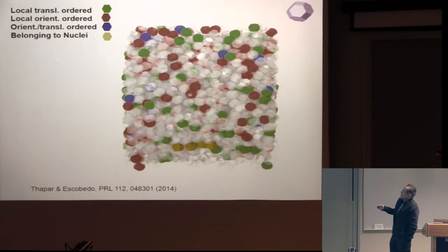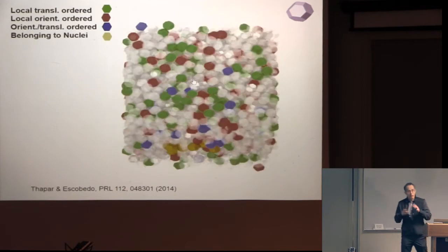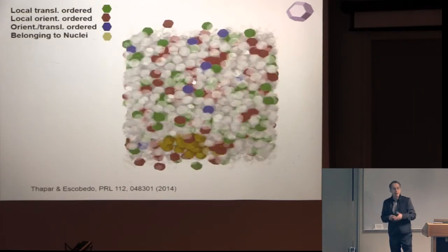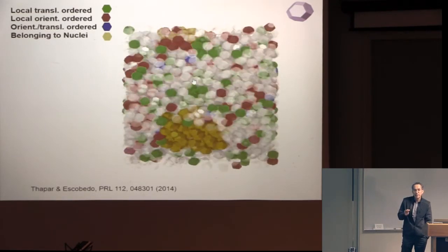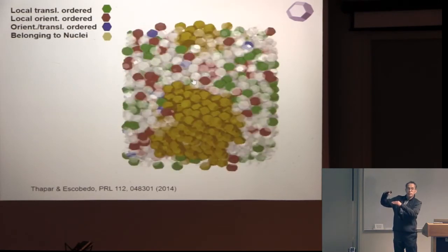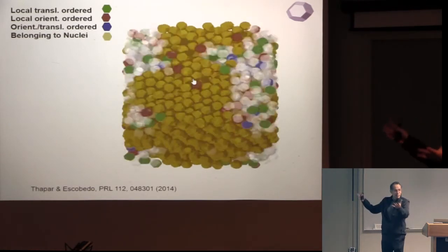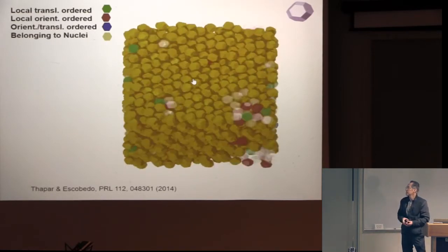This is just a movie for this truncated octahedron going from the isotropic phase to the rotator phase. And we have methods that allow us to compute the rates. And we can tell you that the rates are much faster than crystallizing, say, hard spheres. Which is much harder to do is to understand why. There is something going on in the isotropic phase that's making these entropic nucleation barriers much smaller. It's a long story, but we think it has to do with productive fluctuations in these orientations produced by these entropic bonds.